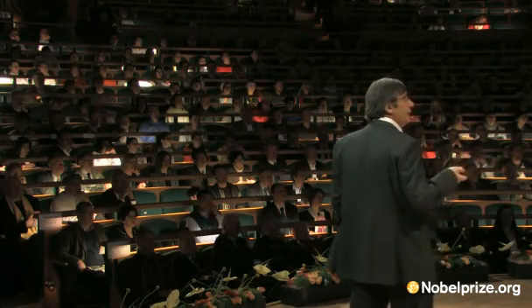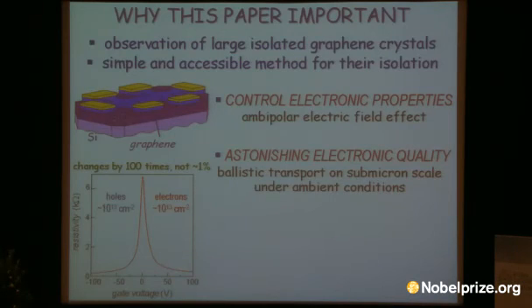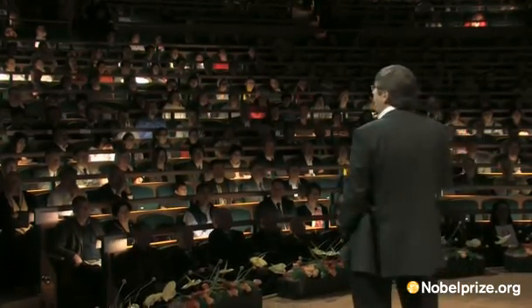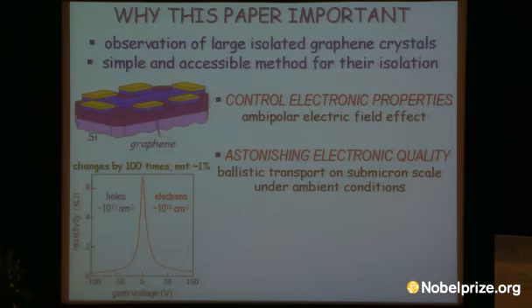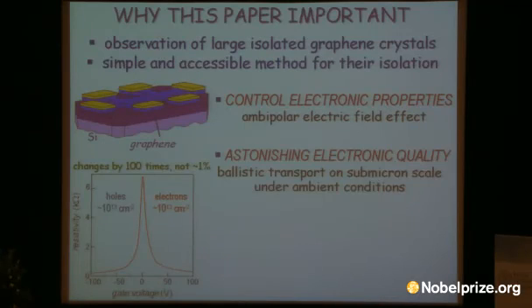Most important, probably, is the quality of the material. People normally know that the thinner the film, the worse its properties. Here you get a monolayer, not in high vacuum, not at low temperatures, under ambient conditions, with a lot of adsorbates, with a lot of lithography residues on a rough substrate. And despite that, electrons travel through like bullets without experiencing all the weather outside. Even with the benefit of hindsight, you can't predict that it would happen for a monolayer. Let me put it this way. If the quality of graphene were 100 times less than we reported in our first paper, I wouldn't be standing here. The quality is very important, and many phenomena we found are due to quality.